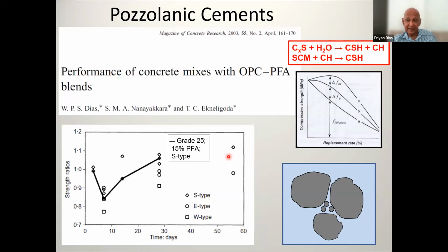So one very practical example of long-term strength is that occasionally the 28-day strength fails. So you have grade 25. If you do all the calculations, the maximum grade you can assign is something like grade 24. But if you happen to have used 15% or 25% fly ash, then you can argue that the 56-day or 91-day strength will satisfy grade 25. So it's always in this region that is practically useful.